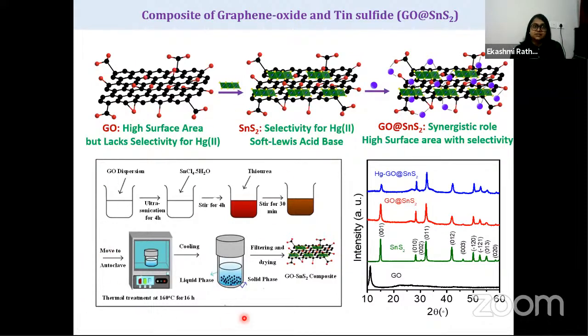I synthesized this material in the laboratory by taking the graphene oxide dispersion, then using precursors like tin chloride and thiourea, all dissolved in water. Then we transferred this solution into autoclaves, which are like tiny pressure cookers that we use in the lab. We did the thermal treatment at around 160 degrees Celsius for 16 hours, and we found that the liquid phase and solid phase separated. We filtered and dried it, and it led to the formation of the desired compound, graphene oxide and SnS2.